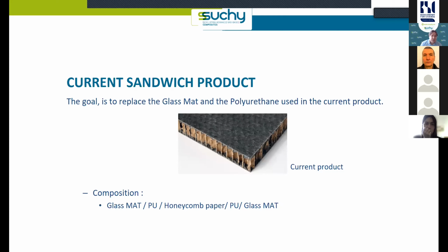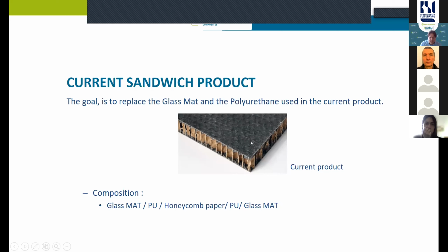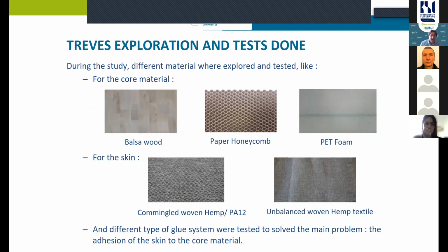We were actually at Treves producing an alternative which was made of 100% polyurethane, but in terms of cost and mechanical properties, we were slightly below this solution. So it's a glass mat, random orientation, with fibers of about 15 centimeter long, and the polyurethane is a binder. So we tried within the Suchy project different approaches, but definitely the most competitive one with the highest mechanical properties, in our case where we are maintaining rather flat surfaces, paper honeycomb is most of the time the most competitive spacer. And we've been playing with unbalanced woven hemp textile and commingled woven hemp, knowing that we focused mainly on the second one.